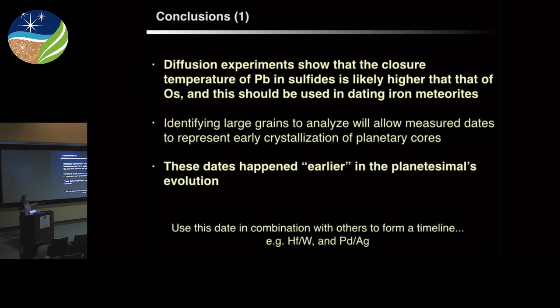Okay, so here's a couple of conclusions from this first series of experiments. They show that the closure temperature of lead can be quite different, and I would recommend that as people continue to try to do lead dating on iron meteorites, they refer to this type of closure temperature. Identifying large grains will allow us to pin to a physical process of solidification or close to that. And not only that, if this closure temperature is at a higher temperature than we had said before, it's sampling a moment earlier in that planet's life. So this idea that we're measuring earlier things, where things are happening faster, can be tempered with the idea that we're also measuring a higher temperature, a moment earlier in that planet's life.